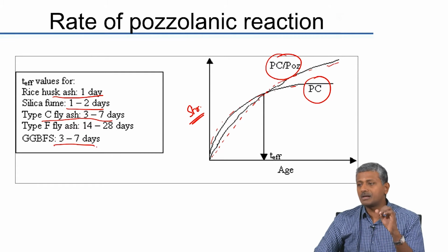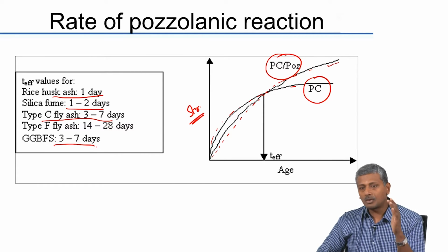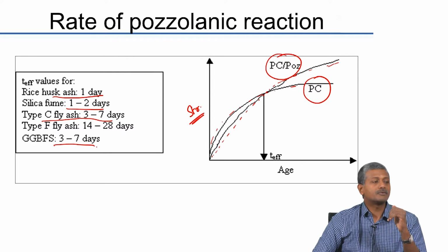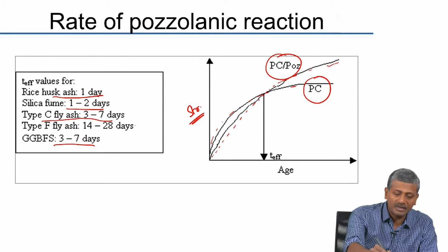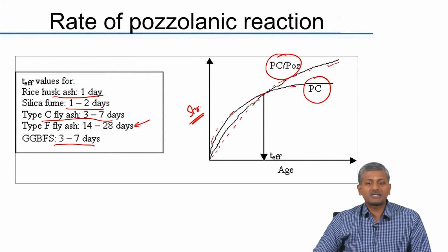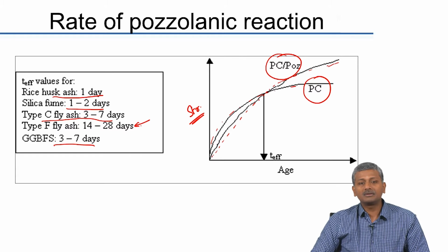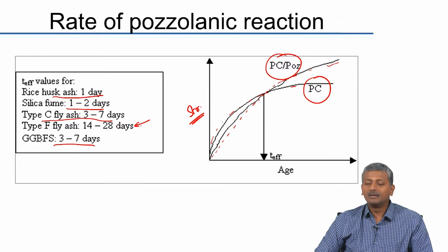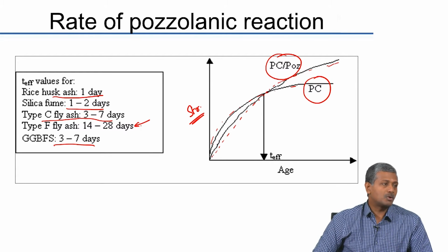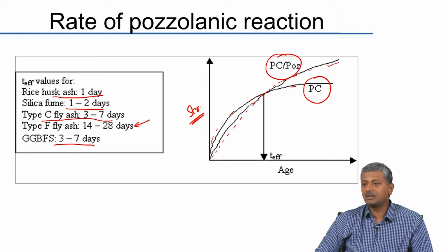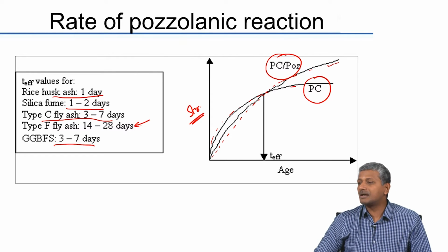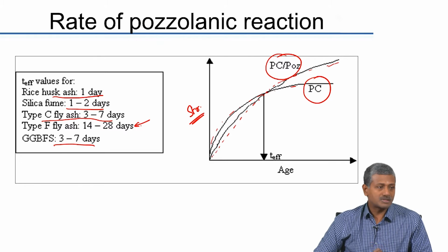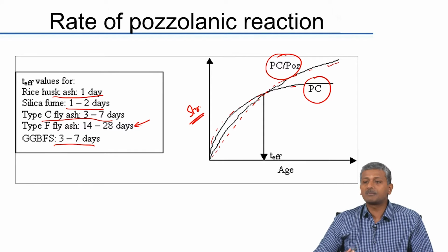That means there is a marginal reduction in your heat of hydration or marginal reduction in your rate of strength development. But with type F fly ash, you can be substantially delayed with respect to your strength development. You may actually be able to attain equivalent strength as a Portland cement mortar only between 14 and 28 days. Now, all these numbers are given for typical replacement levels of these materials. Okay. Obviously, these will not hold good if you keep changing the replacement rate.